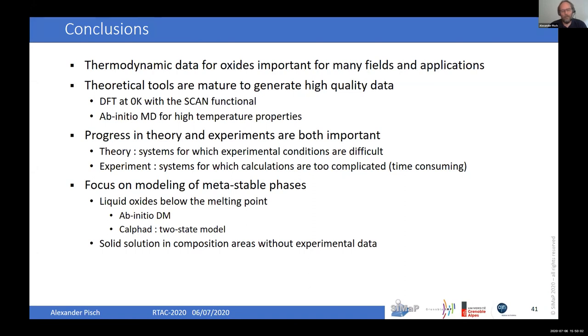And I think my focus in the future will be modeling of metastable phases, liquids, and especially liquid oxides below the melting point. It can be done by ab initio molecular dynamics, and then by the CALPHAD two-state model in order to get multi-component systems. But it's also important in solid solution ranges, in composition areas where we cannot get any experimental data. But the models need input values. I think there it is very important to continue this work on modeling of metastable phases.